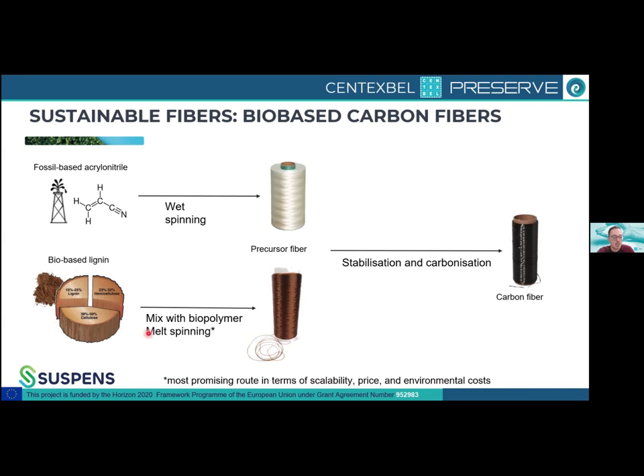So by using this, because producing at 100% lignin is super, super difficult, you are mixing it with another polymer, and in this case, a biopolymer, bio-based polyamide. And by using melt spinning, you can create this precursor fiber, but then again, in the project, with some carbonization, it is then turned into the carbon fiber.